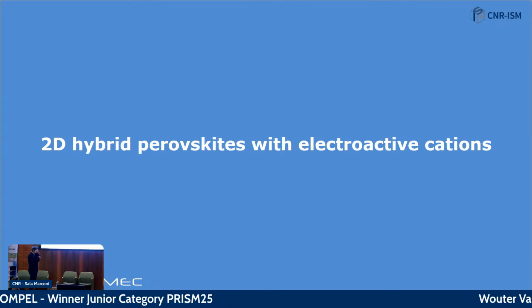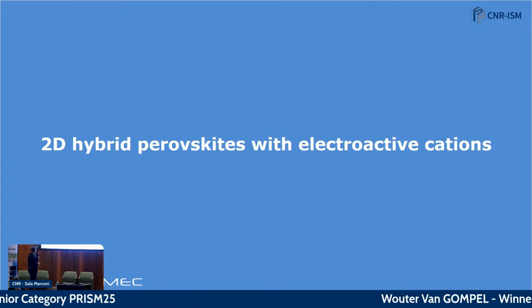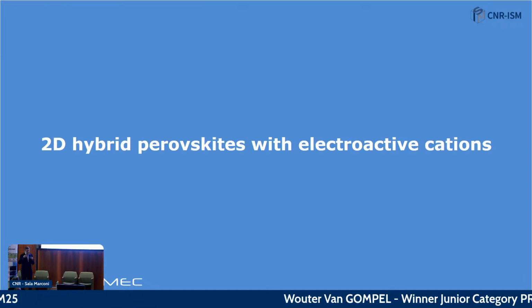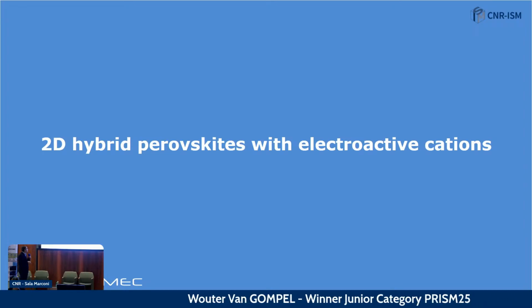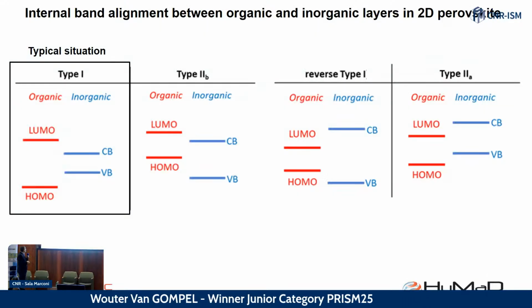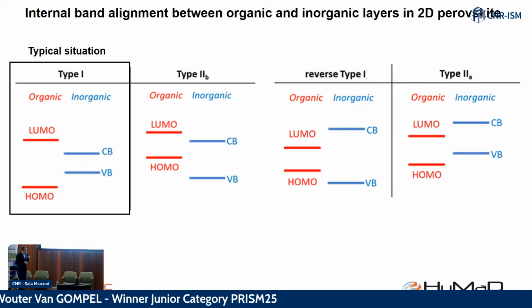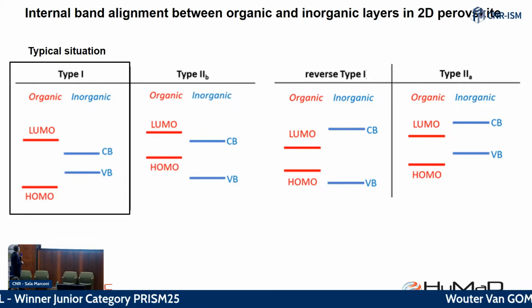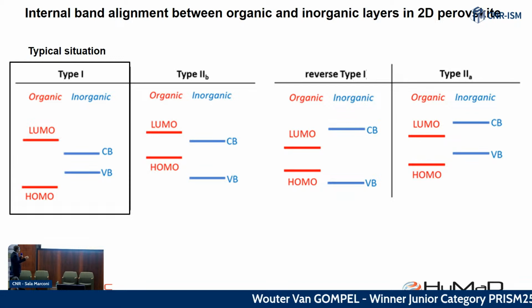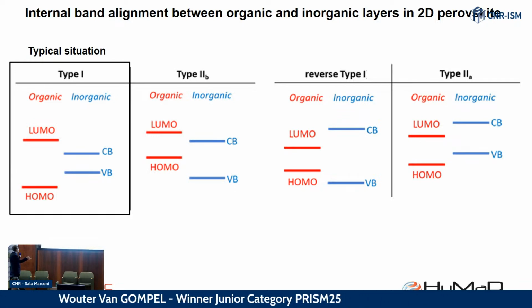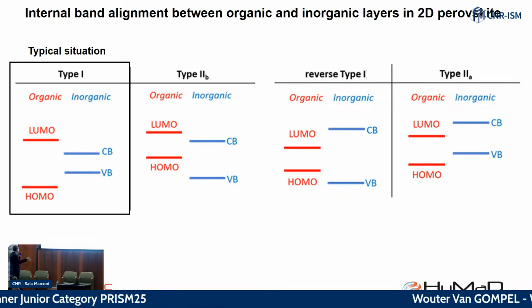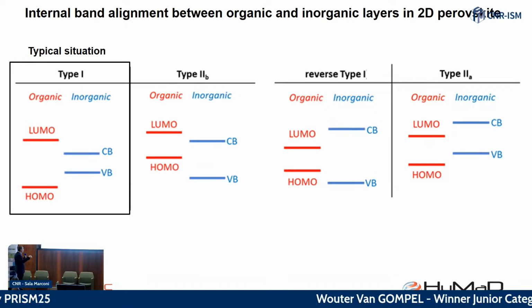So on to some very specific examples. 2D perovskites with electroactive organic cations. What do I mean with electroactive? Well, the typical situation is a type 1 internal energetic alignment between the organic and the inorganic, which means that all the interesting processes happen on the inorganic. Once you excite the material, the charges remain on the inorganic. The organic has a much too wide gap to play any role in the process.